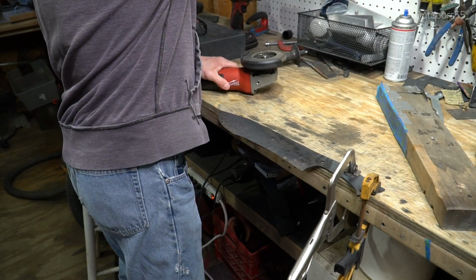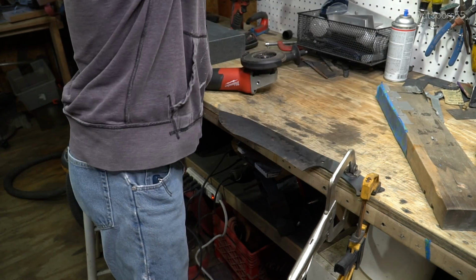Then we want to get this into the tempering oven as quickly as possible. We're going to be using our home kitchen oven, and we're going to be doing 2 1-hour cycles at 400 degrees. So what that means is we'll leave the knife in the oven for 1 hour at 400 degrees, then we'll take it out, let it cool to room temperature, and then put it back in the oven for 1 hour at 400 degrees.